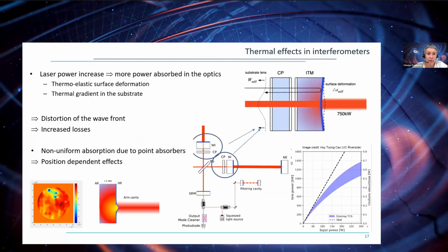Now I'm going to talk about the other upgrade, which is about the laser power increase and its induced effect. So the laser power has been increased in all interferometers, and this means that more power is absorbed in the optics. Our optics have very low absorption, of the order of the ppm, but as we increase the power, the effect of this small absorption has some thermal effect.